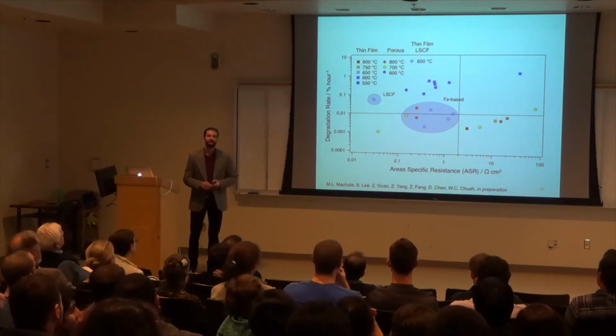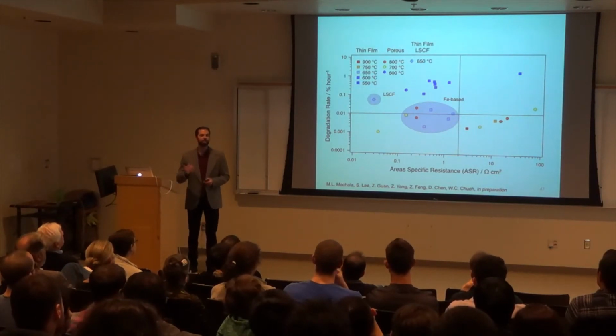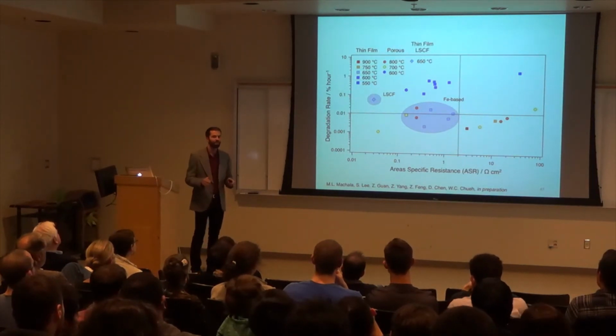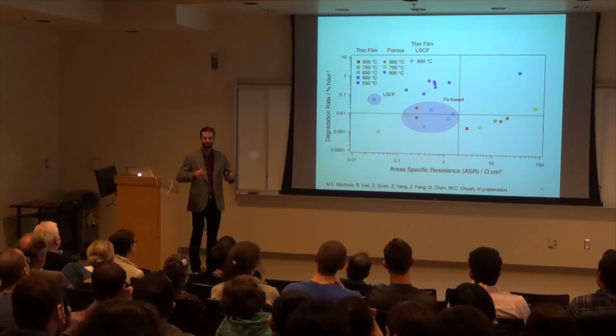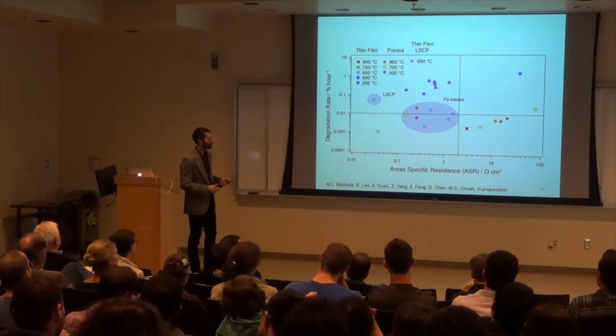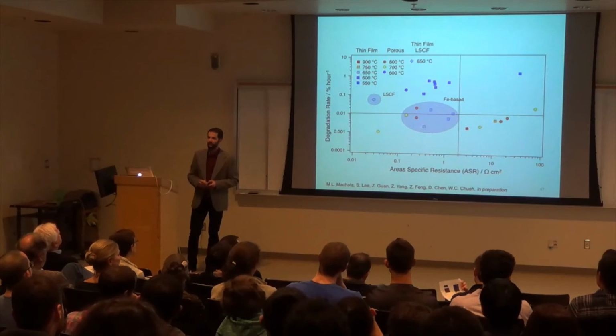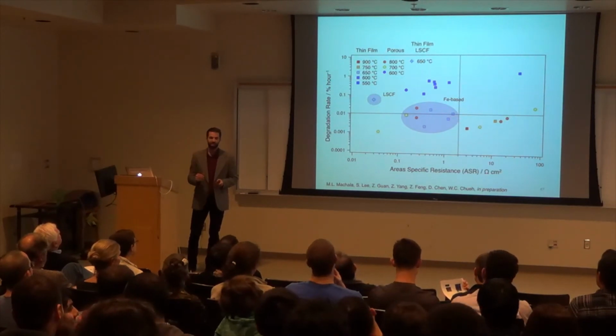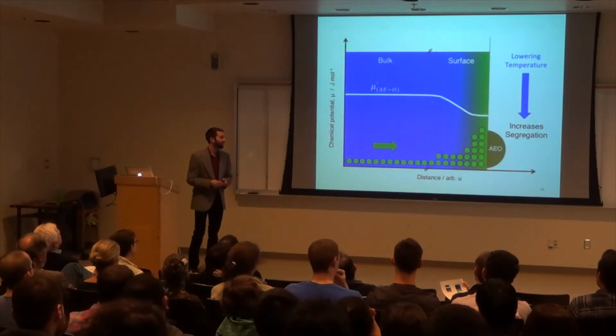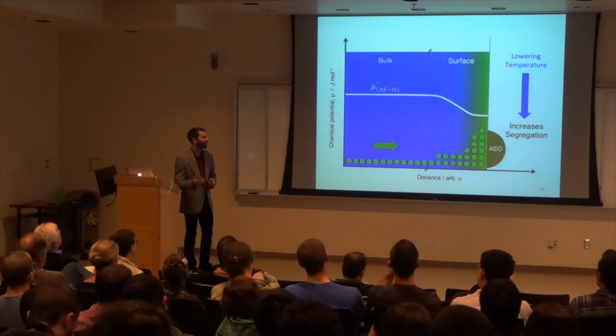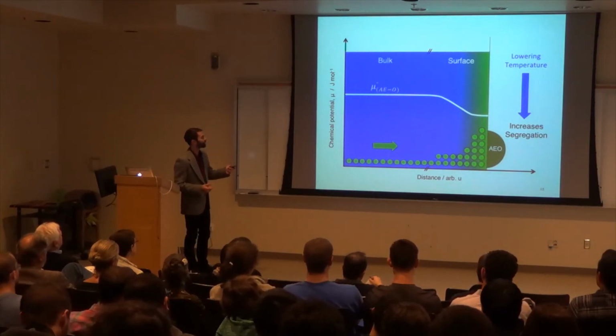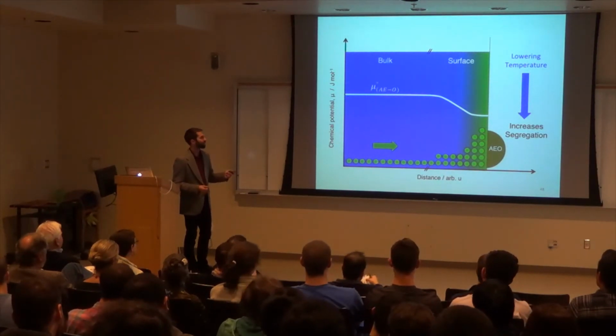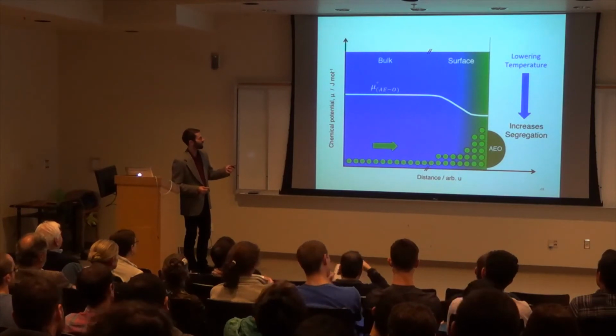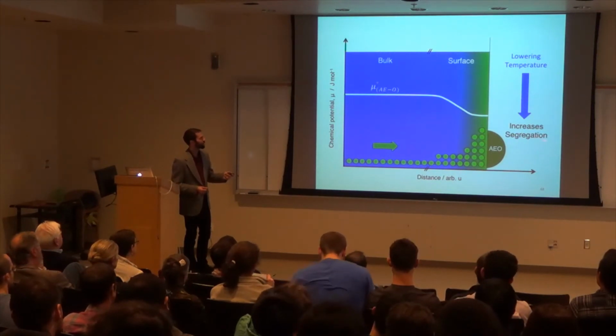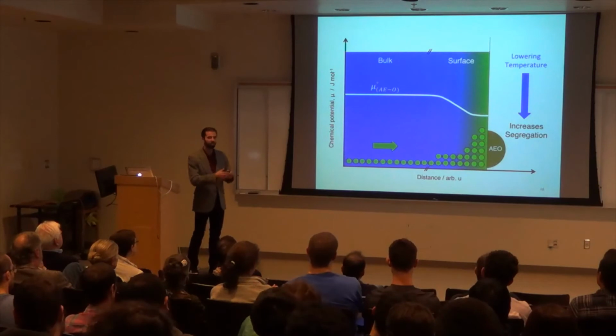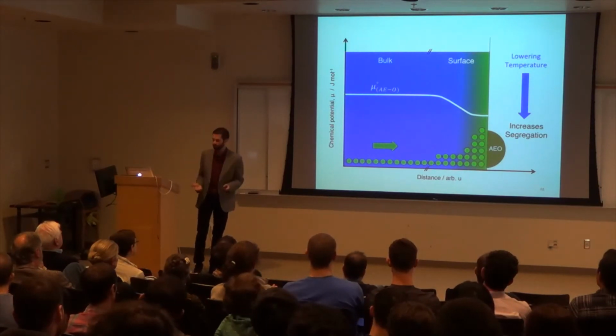But it's also degrading. And remember, this is just a thin film geometry. This is not porous, so it doesn't have the enhancement that having a large surface area does. So we have a highly active material that degrades. We need to do something about that to try to maintain that catalytic activity. Now recall, we have 2 things working against us in this graphic we showed earlier. We have lowering the temperature, increasing segregation, and basically driving these precipitates from forming.